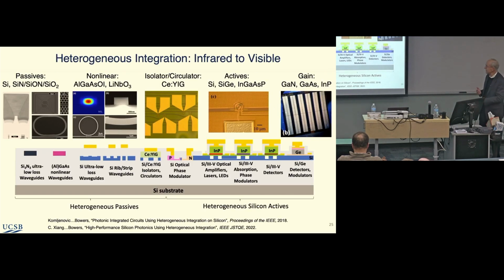By heterogeneous, we mean taking a silicon substrate, all processed in 300 millimeter wafers, giving you all the advantages of a modern 300 millimeter fab. You may have nitride waveguides with very low loss, literally 0.1 dB per meter, and you can make resonators with Qs of 400 or 500 million, maybe a billion. You can combine it with aluminum gallium arsenide, or lithium niobate for that matter, thin film lithium niobate. The advantage is that it's clad in SiO2, so you get very tight confinement of the mode inside these very thin AlGaAs layers and narrow widths, giving very high nonlinearities—we'll talk about that.